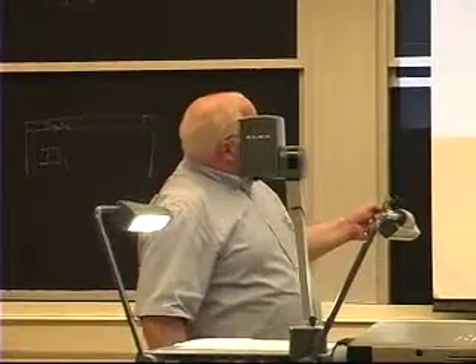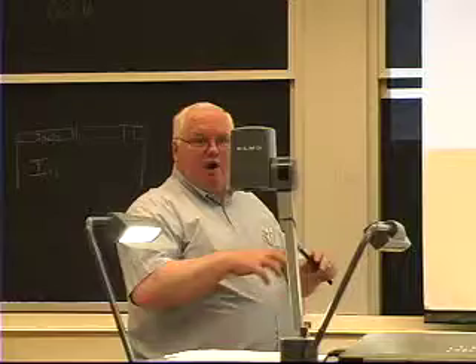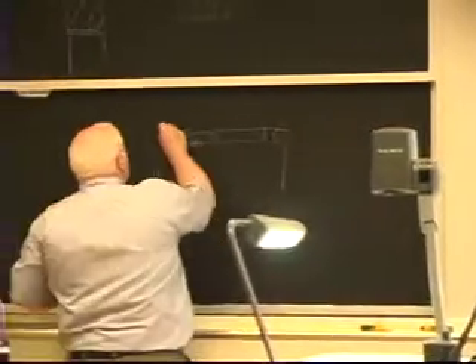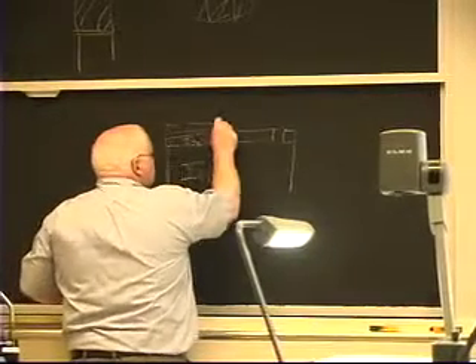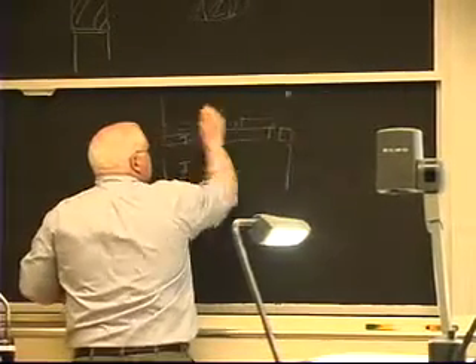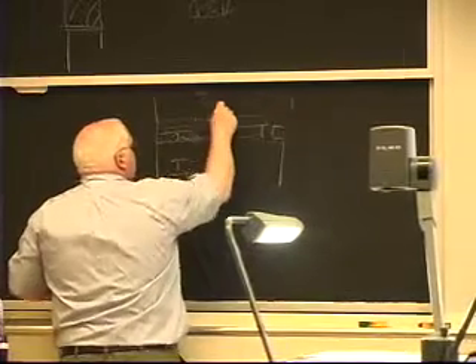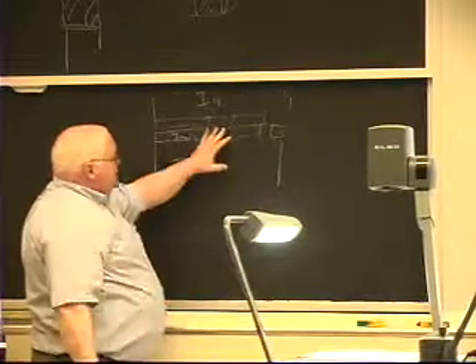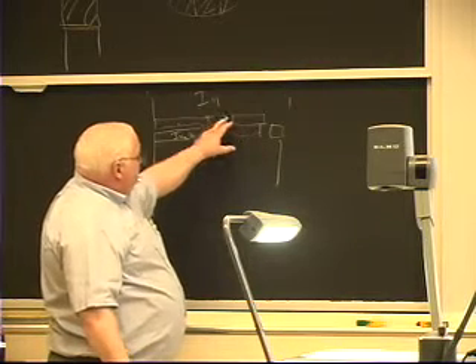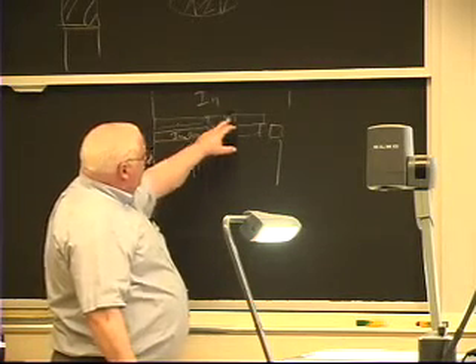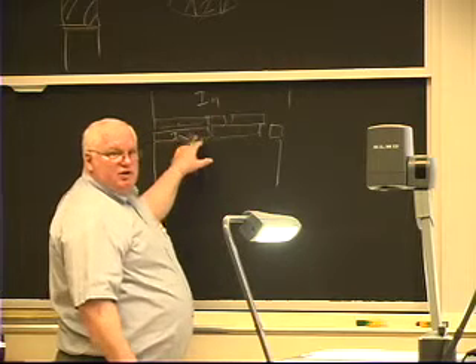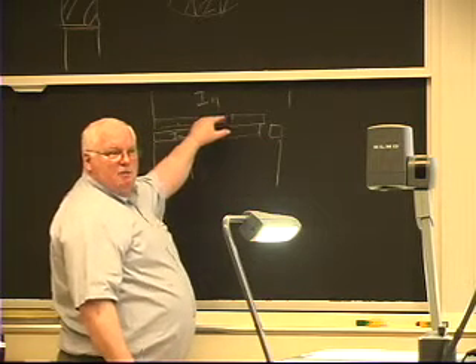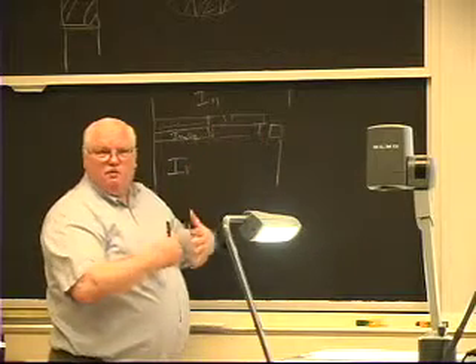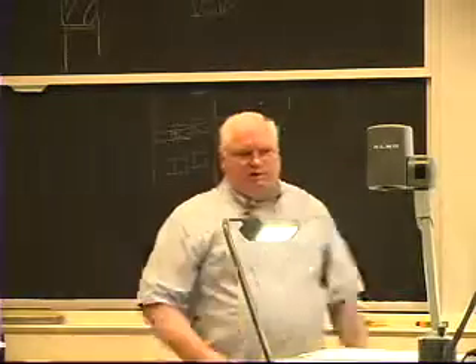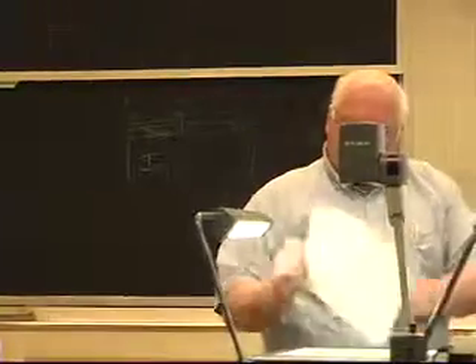If you have a high hardness oxide that won't smear, then all you have to do is break it up, and you'll get the indium from the other side. Of course, you've got some indium here and some here, and this is indium oxide, this is indium up here, and you're trying to squeeze these together. And it turns out there's a paper that I'm not going to go through that some guys out at Berkeley basically said, well, you just look at the statistics of how much new area you have on this and how much of that overlaps this other surface over here, and you can prove, actually I guess I can show it to you. I think it's on the back page of this.